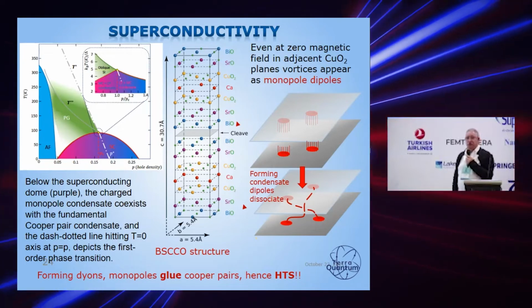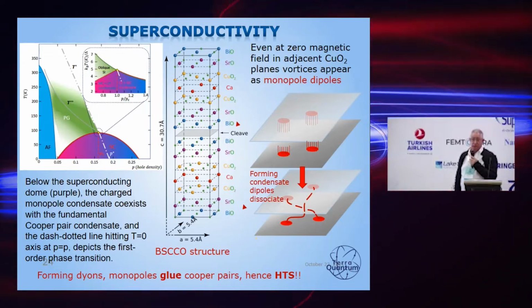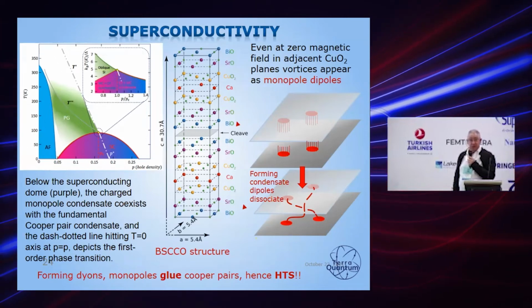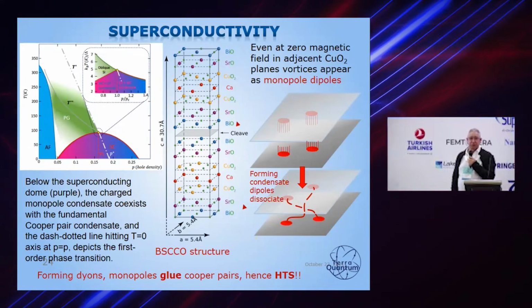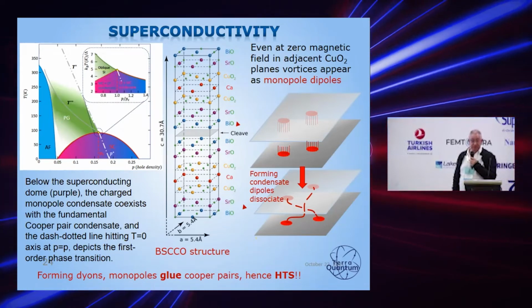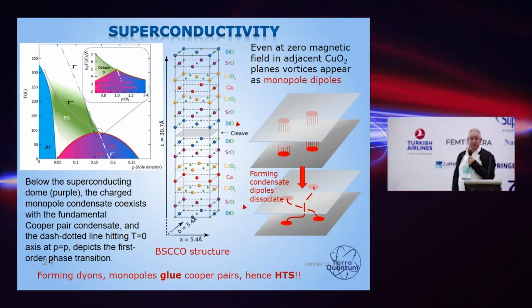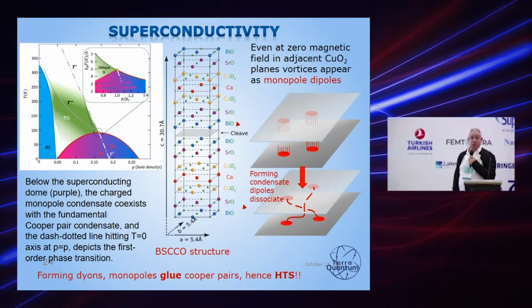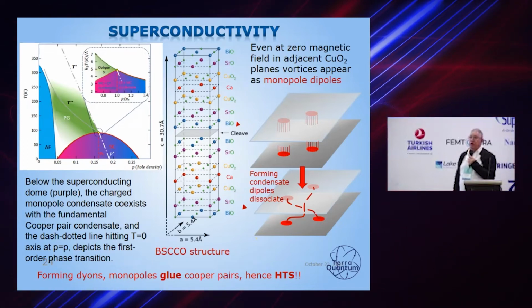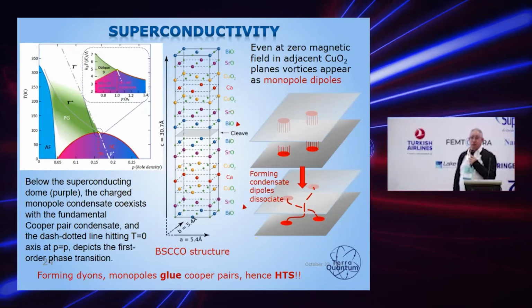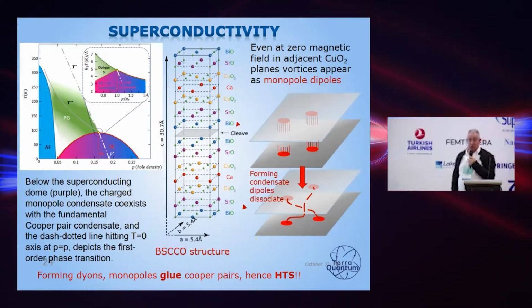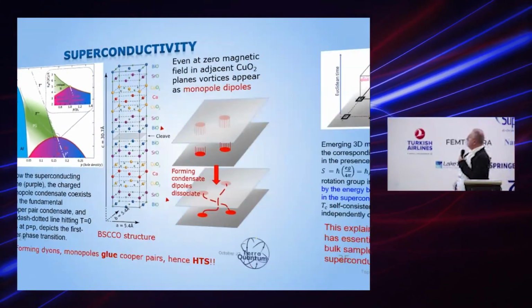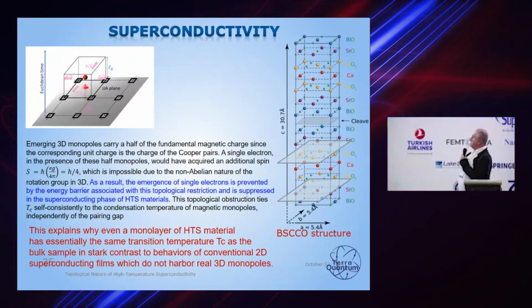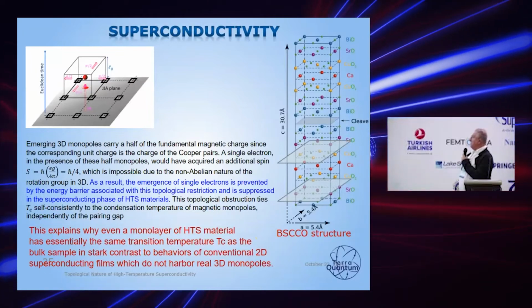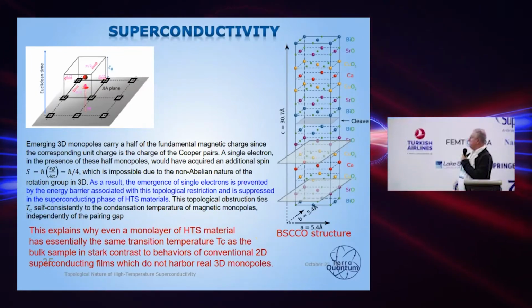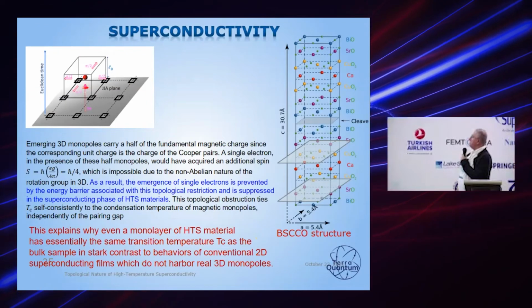If we take an ordinary superconductor, you will never see that. If you make a thin film of an ordinary superconductor, its transition temperature is going to be much less. And the explanation, I repeat, is just this monopole gluing; it's enough to have just two copper oxide planes. We don't need any more. Okay, let's move on. So this is just to repeat once again that even a monolayer high TC material shows exactly the same transition temperature.